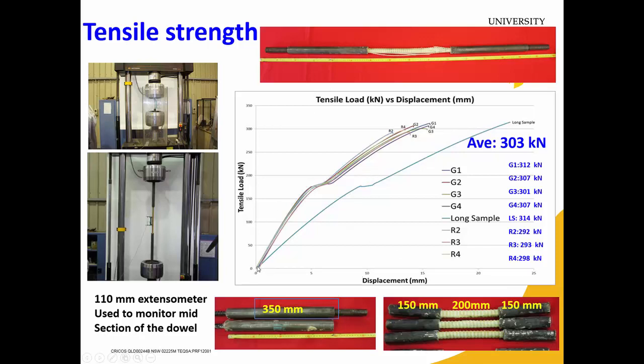You can see that the tensile load increases, and then you have a failure around 30 ton. So the average value is 30 ton. And this is the sample after failure. So you have tensile failure in the sample.